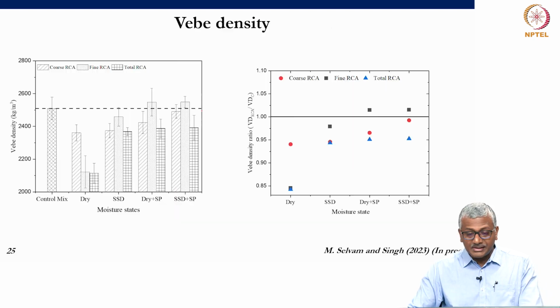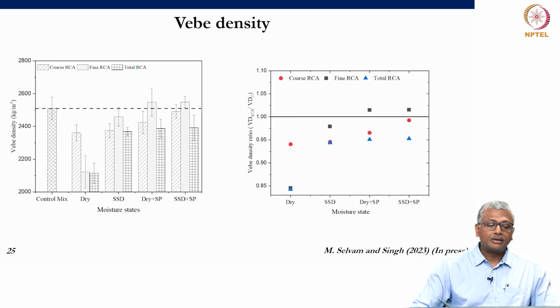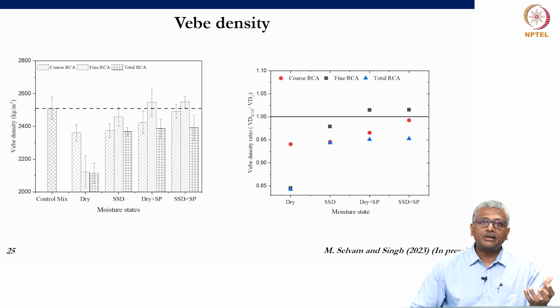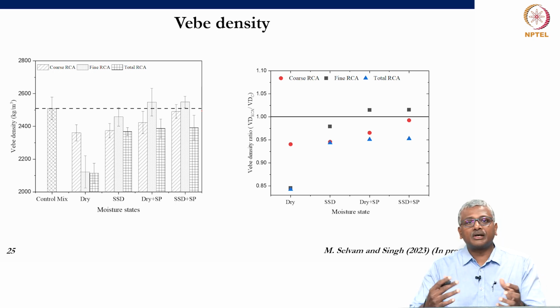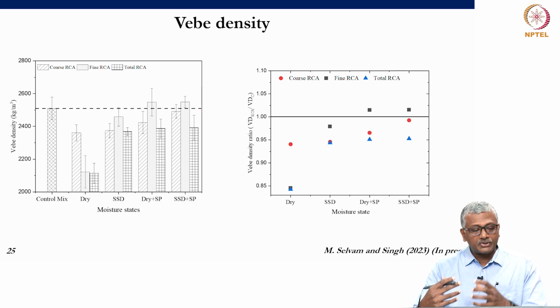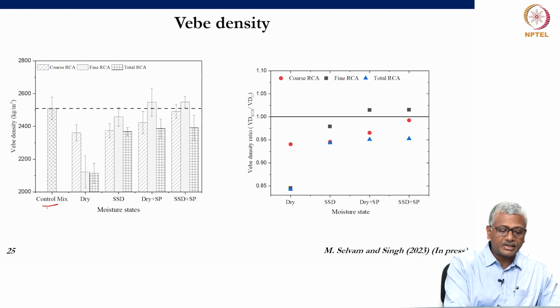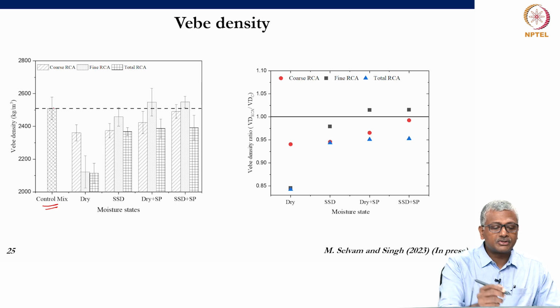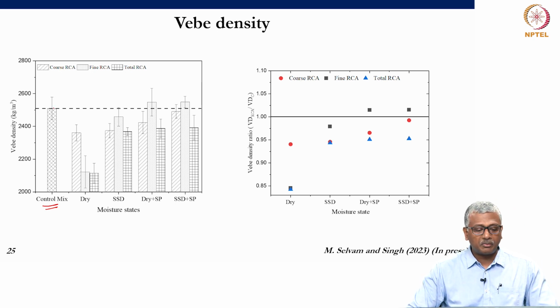Okay. So, in this study what was done was the Vebe density. Vebe basically is the apparatus which is used for determining the workability of very fresh concretes which are harsh. Okay. Fresh concretes which are very harsh. So, in such cases what was seen was, for the control mix with natural aggregate, the Vebe density was nearly about 2500 kilogram per cubic meter.